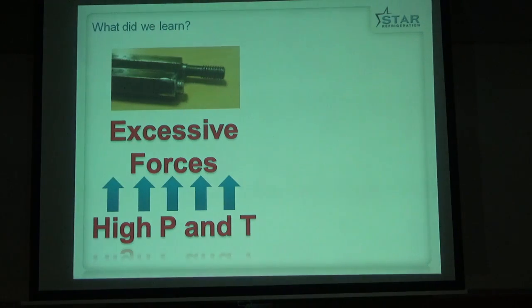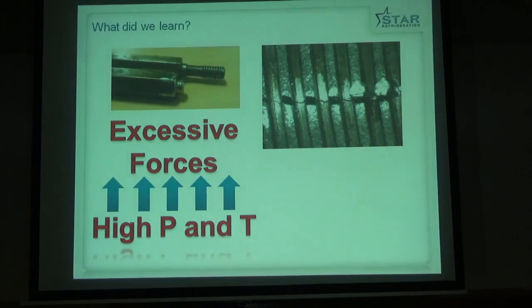Also, other components highly stressed. This is a push rod that moves the slide valves in the compressor, before and after, fractured because of the high forces. So we're using a strengthened push rod. This is a tube from one of the shell and tube condensers. It's a finned tube, and there was a defect in the material. So the tube was faulty. If we'd been running at normal operating conditions, we would probably never have known this. But because we're running at 90 degrees C condensing, which is about 65 bar, the defects weakened the tube to the extent that it leaked.